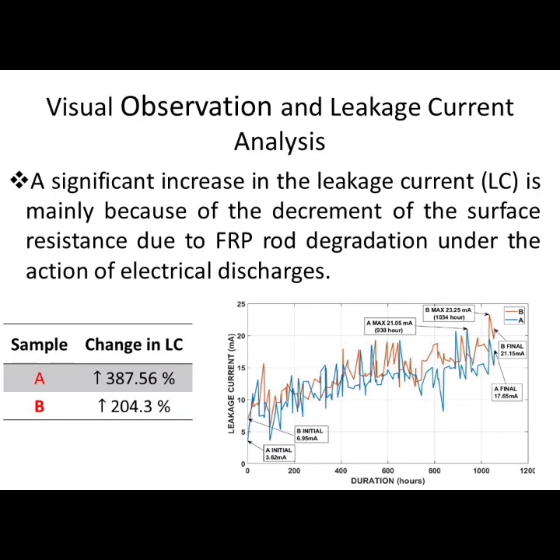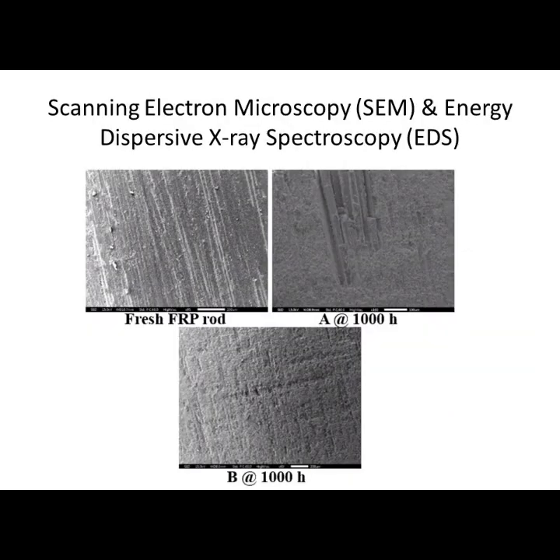However, this increment was higher in the normal sample compared with the tracking resistant sample, indicating a significant degradation in the normal sample compared to the newly developed sample. So now the scanning electron microscope equipped with an energy dispersive X-ray detector was used to evaluate any morphology changes or the elemental composition on the surface of the FRP rod samples.